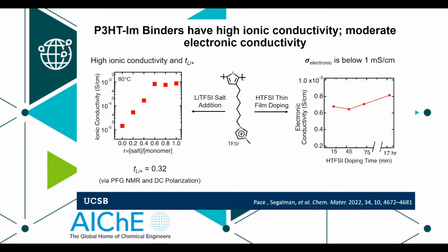Conjugated backbone will help give us electron conductivity. We add something that looks like an ionic liquid as a side chain, which allows us to tune the ability to dissolve salts like ionic liquids will let you do. If you look to the left, we get fairly good ion conduction. That's 10 to the minus 3 at various salt loadings with a good transference number. That is good enough to run a battery, actually. The right-hand side is the electronic conductivity, which isn't great. It's approaching good enough because we're getting some of the connectivity we need of all of those aromatic backbones to get charge from one electrode to the other. I'm not ending my talk here, so clearly there's a problem.